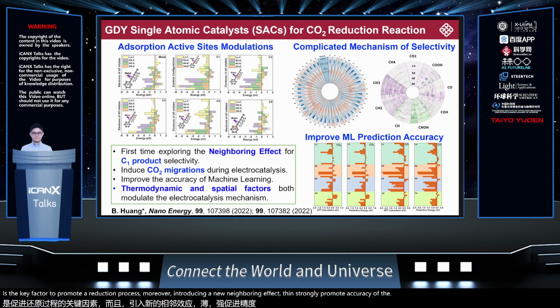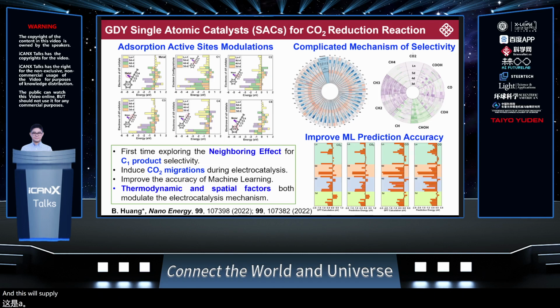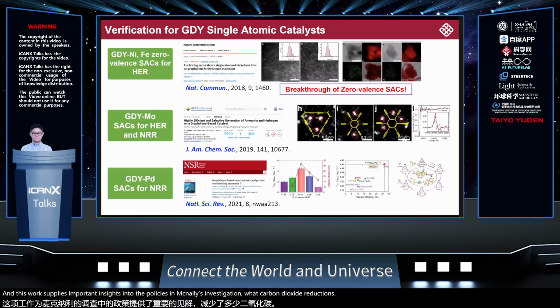Meanwhile, we also investigate neighboring effects of this SAC. Interestingly, the initial process of carbon dioxide adsorption is more favored on the carbon alkyl chain. However, the metal sites dominate the following reaction steps during the catalysis. This means that diffusion of the carbon dioxide among different active sites is the key factor to promote the reduction process. Moreover, introducing the neighboring effect can strongly promote accuracy of machine learning prediction in the future. And this work supplies important insights into the catalysis mechanism investigation for carbon dioxide reduction. Our theoretical investigation of graphene support atomic catalysis is also verified by experimental collaborations.